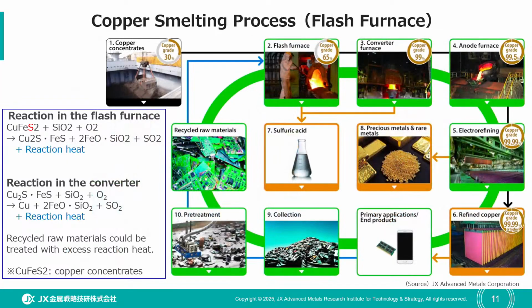So, now I would like to talk about the production flow of copper cathode at a smelter using flash furnaces. The flash furnace is a major copper smelting process around the world. The copper concentrates are fed to the furnace with oxygen-enriched air. And in the shaft, the concentrates, which consist of copper 30%, iron, and sulfur, are instantly oxidized. Copper concentrates are melted and separated by their own reaction heat into copper matte with a grade of 65% and slag. The copper matte is transferred to the converter furnace and anode furnace and refined to a purity of approximately 99.5%. And anode plates are refined in the refineries, which is the tank house, by electro-refining, and copper cathode with a grade of 99.99%, 4N9, is produced as a final product.